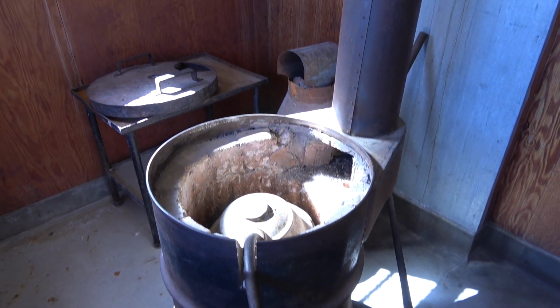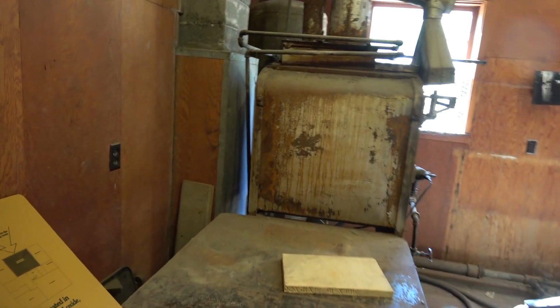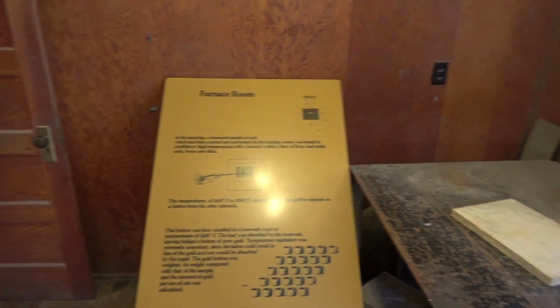The amalgam cakes, which were 50% gold and 50% mercury, were crushed and packed tightly in a cast iron retort pot. Small holes were punched in the amalgam to form gas vents to allow the amalgam to heat more evenly and more rapidly. At the end of the process, the retort pot was removed from the furnace and allowed to cool. The mercury, which had been recovered, was weighed and returned to the mill for reuse in the milling operation.